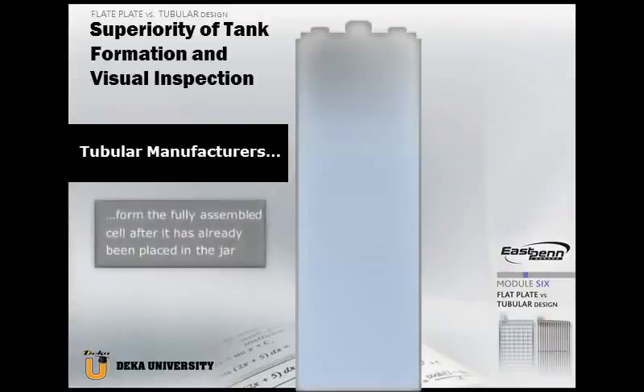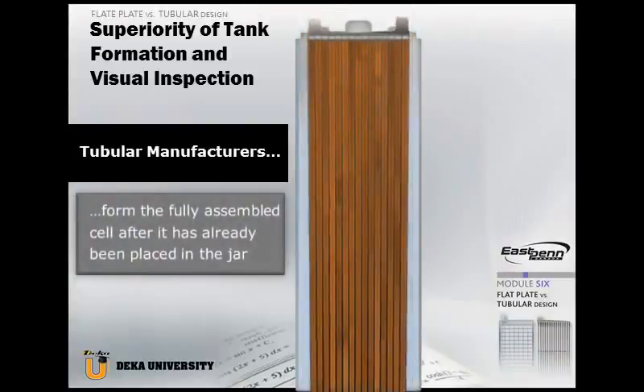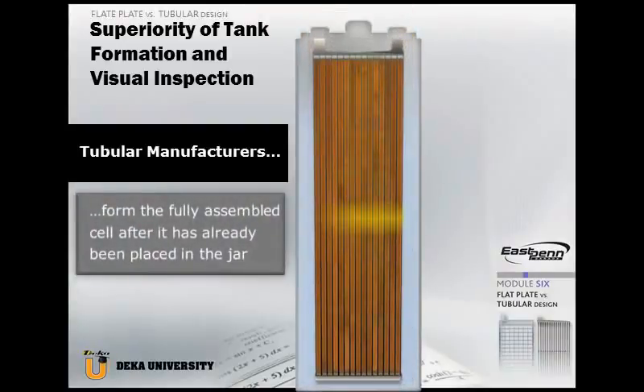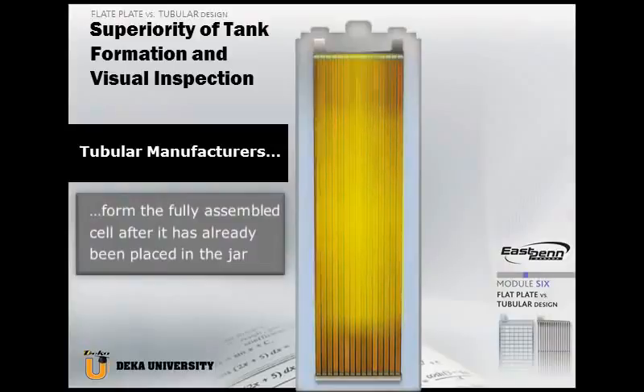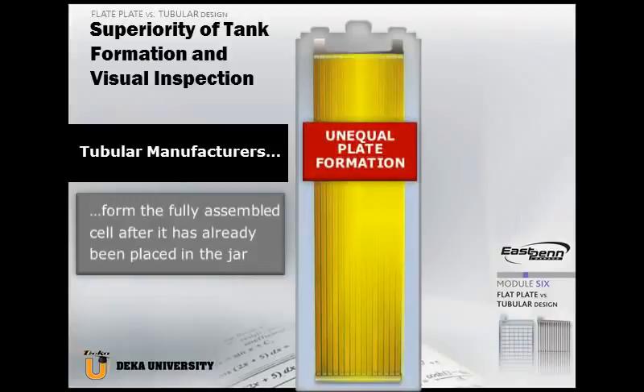Tubular manufacturers form the fully assembled cell after it has already been placed in the jar. There is therefore no way of inspecting the plates to evaluate the completeness of plate formation without tearing down the battery. This creates an environment more prone to unequal plate formation, leading to unequal cell-to-cell voltages, which is especially detrimental to the battery during the charging process.